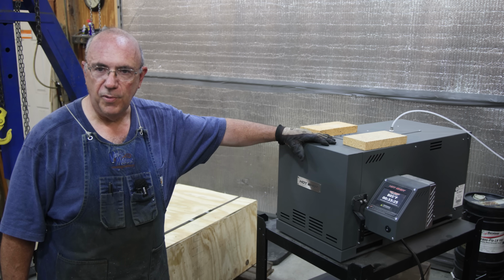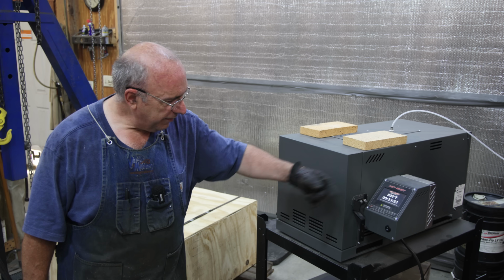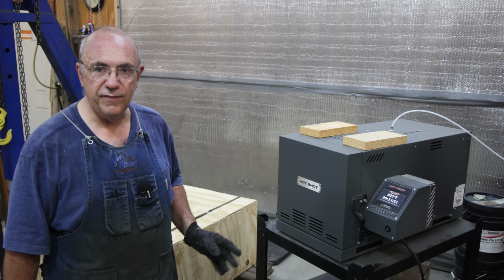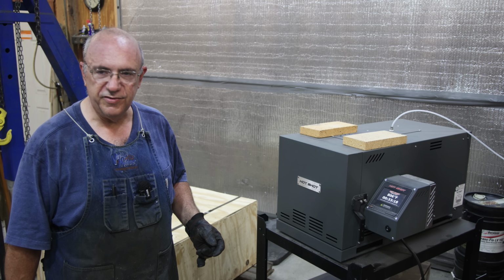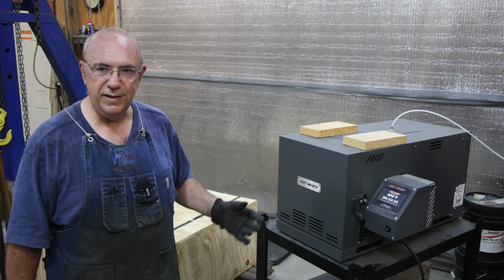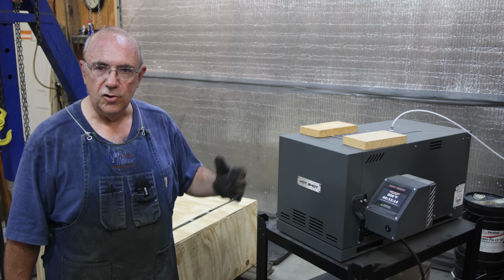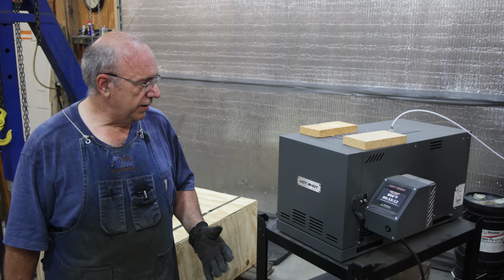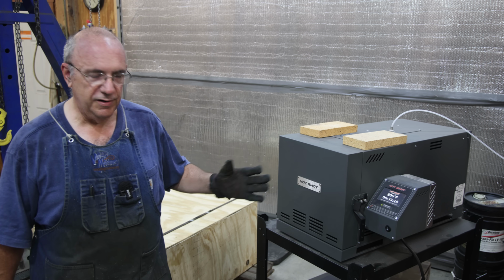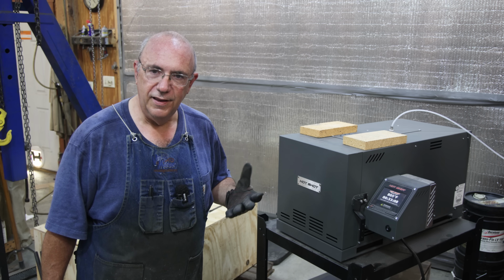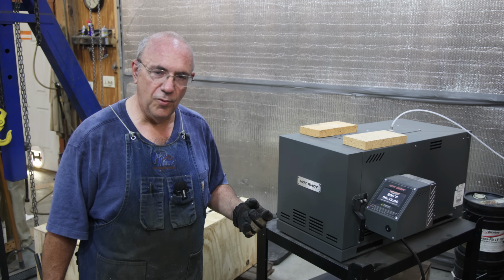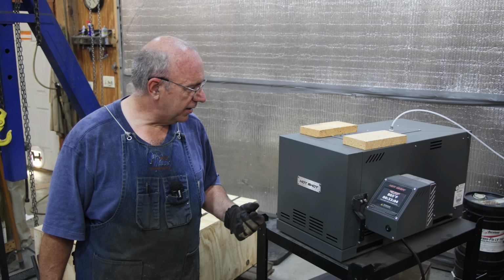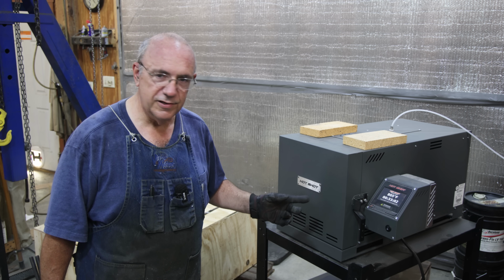So we've been letting these parts soak in here at around 800 degrees now for about 45 minutes, which should be good for the tempering process. The whole idea here is you heat it up, you quench it, that makes it super hard. You heat it up at a lower temperature and just let it cool down, and that's going to soften it so it's not super hard. We don't want these so hard that they're brittle. We want to make them tough. So this should get the job done.